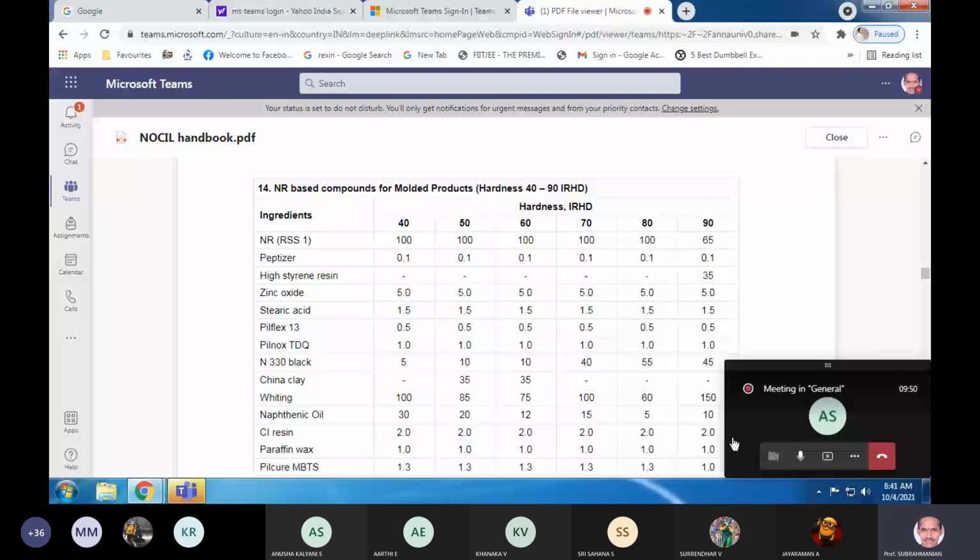Anti-ozonants are governed by some 5 or 6 parameters. Number 1, how well they get into the rubber. And 2, how well they migrate to the surface. And number 3, how they react with the deleterious ozone attack. And number 4, what kind of reaction products form?